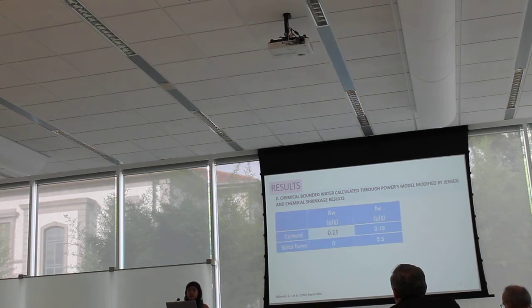Then we have the results of the chemical bound water from the TGA measurements, and as Powers said, it was the same, 0.23 grams per gram, which is what I calculated. The gel water is a theoretical value, also for the silica fume.